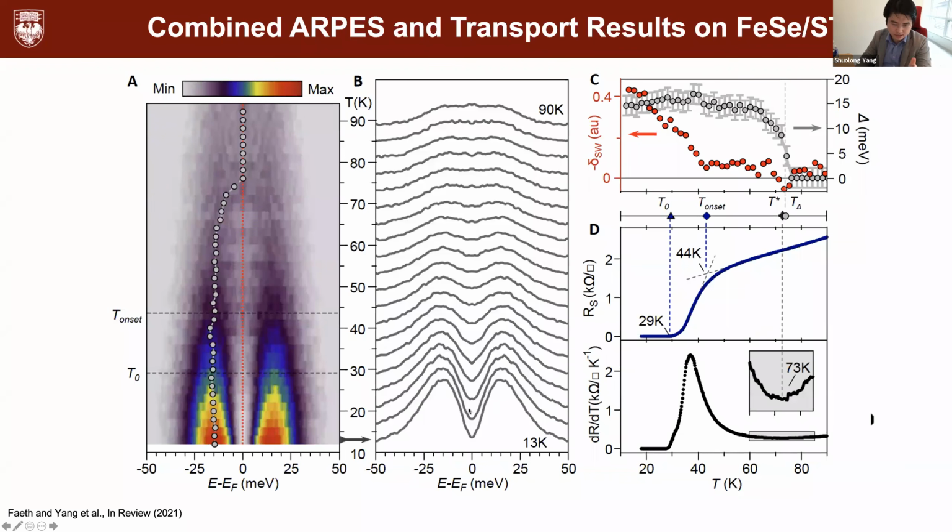And at low temperature, you see this iconic double peak structure. And this is due to the opening of a superconducting gap. And as you raise temperature, this gap becomes less prominent. And around high temperature, maybe up to 90 Kelvin, the gap starts to be not recognizable. And we could try to use the peak-to-peak distance plotted on the top right to indicate the gap closing behavior. Actually, I would like to emphasize that this is not quite a gap closing behavior. What we have observed is actually a gap filling behavior, where the peak-to-peak distance basically stays unchanged until the spectral weight in the middle just fills up the gap. So it's a very peculiar, unconventional behavior if you compare to conventional superconductors.